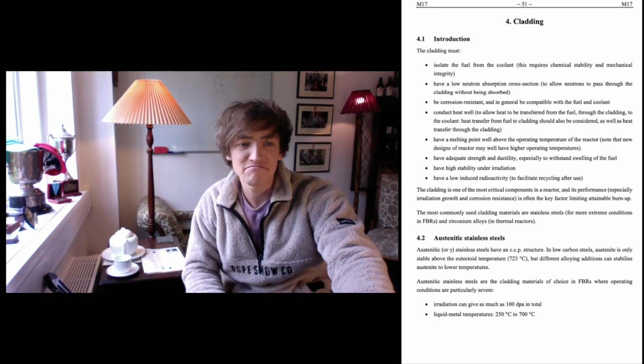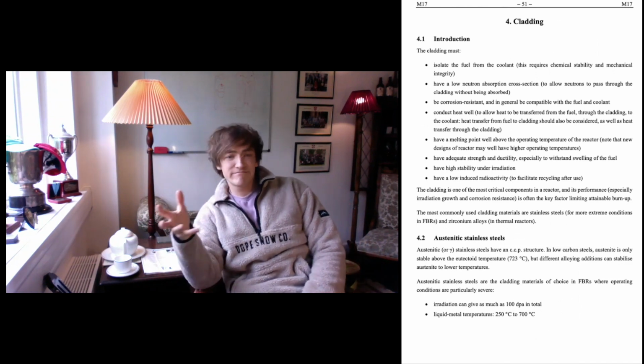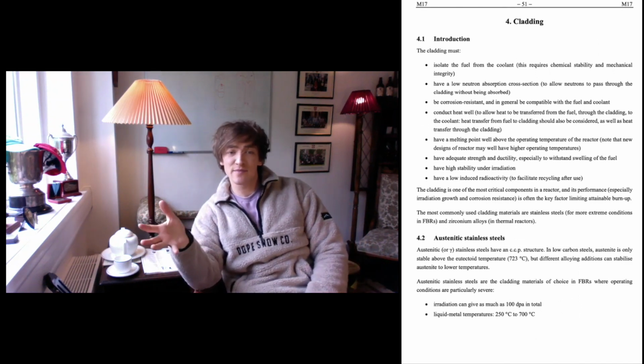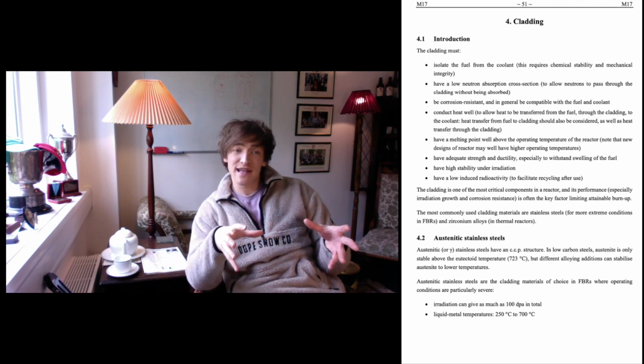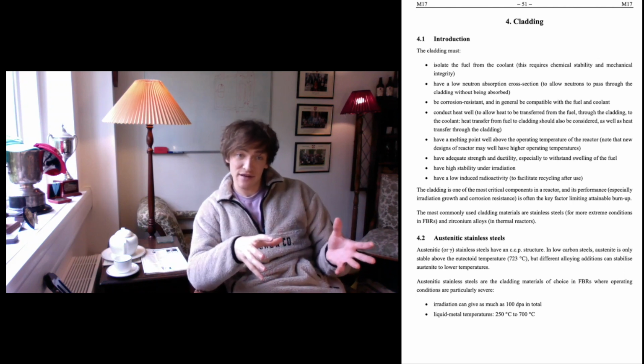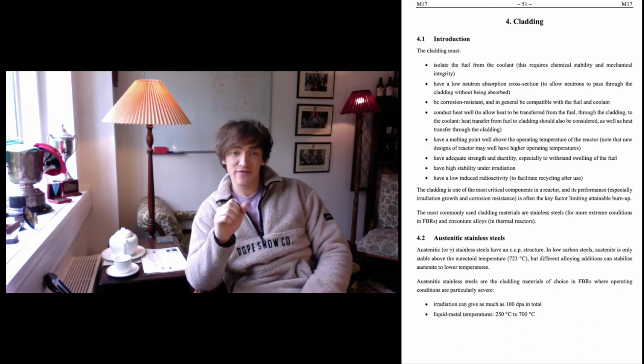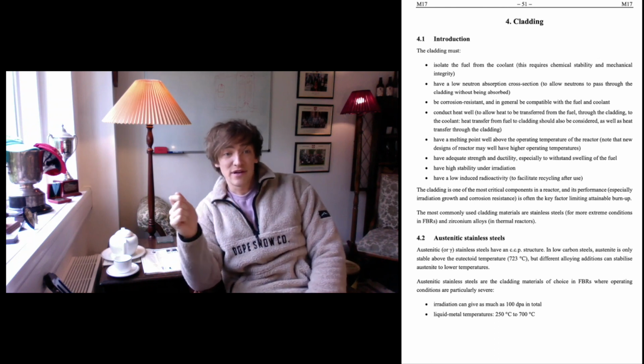So, austenitic stainless steels are CCP structure, so cubic close packed. In low carbon steels, austenite is only stable above the eutectoid temperature, which is around 723 degrees Celsius. But different alloying additions can stabilize that austenite phase at lower temperatures.